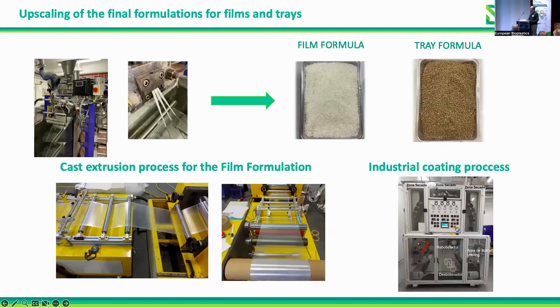By doing so, we decreased oxygen permeability and water vapor permeability, and increased water repellency. We have also developed different coatings for PLA films using different methodologies such as PLA plastisols, PLA emulsions, and PLA hot melt. We then upscaled the processes to obtain our final demonstrators, first upscaling the copolymer by reactive extrusion, then preparing and upscaling all formulations by compounding in extruders.